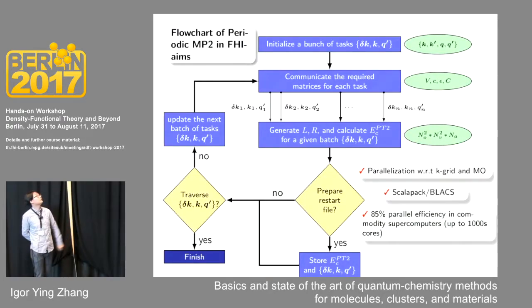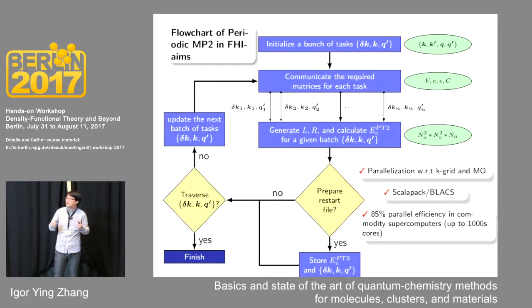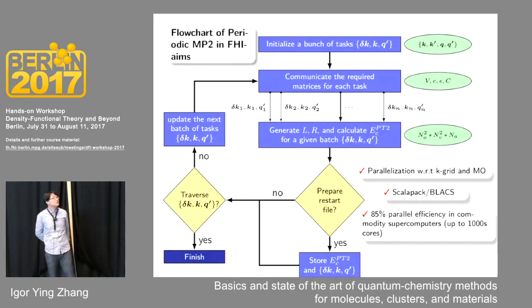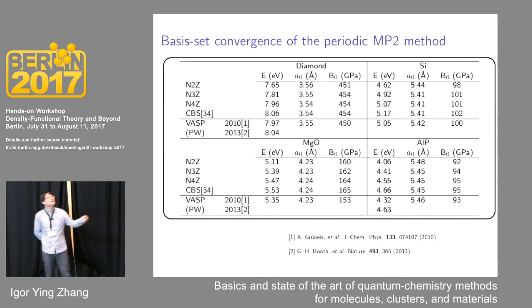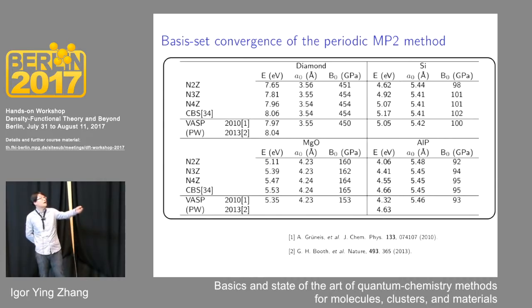This is the flowchart of periodic MP2 implementation in FHI-aims code. The parallelization is designed with respect to both k-grid and molecular orbitals. In order to achieve highly efficient distributed-memory calculations, we use ScaLAPACK and BLACS to distribute four-center integrals and the corresponding three-center RI coefficients. We have demonstrated that very high parallel efficiency can be achieved on supercomputers up to several thousands of CPUs. Here I selectively show the basis set convergence of our periodic MP2 results for several bulk crystals with cubic structure: diamond, silicon, MgO, and AlP.